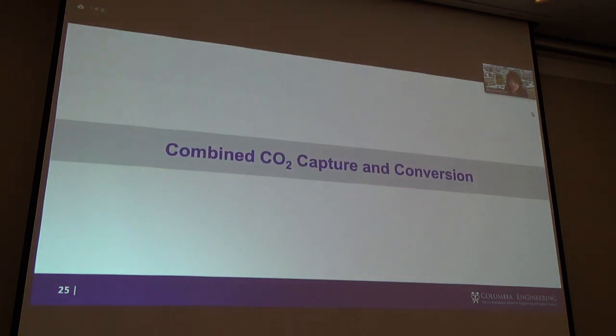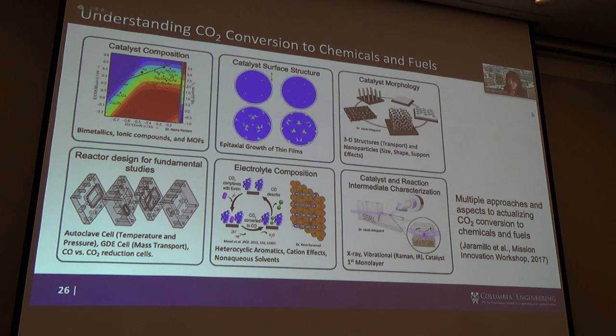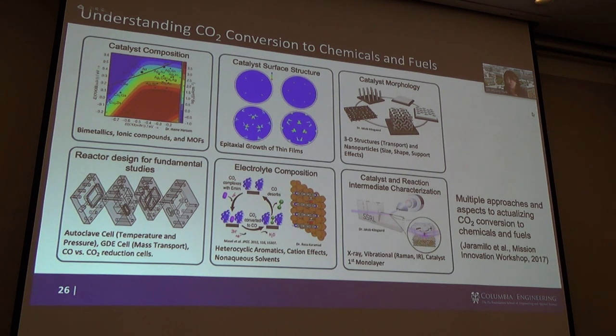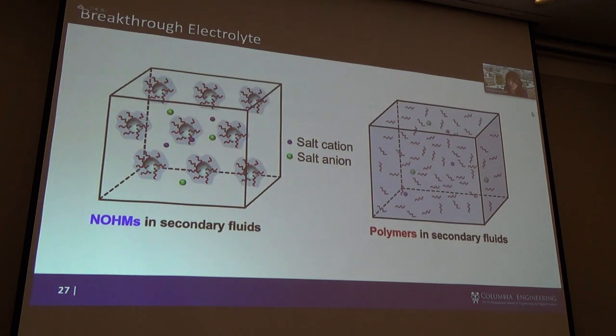So finally, I want to touch upon a little bit on how to combine CO2 capture and conversion. Looking back at these materials, we start thinking that, once we capture CO2, if we have to convert it to chemicals and fuels, what is the pathway we want to use? One of the pathways you can use is electrochemical reduction of carbon dioxide. There is a lot of research, especially in South Korea as well, looking into different catalyst development as well as reactor design and so on. So one of the areas I'm working on is electrolyte design. What we started thinking was, going back to our NOHMs study, these materials are quite unique and quite immiscible in water. So what if we use them as electrolyte additives? So that we can really increase the CO2 solubility in the electrolyte, and then we can deliver the CO2 to the surface of the catalyst most effectively.